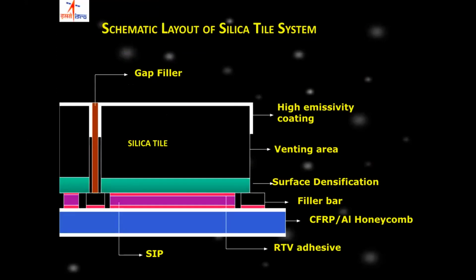And this is the mounting scheme of this tile, because we are fixing the tiles on a metallic structure of the capsule. So you can just appreciate the thermal expansion. Metallic materials expand a lot, but ceramic materials expand very little. So when you are fixing these ceramic tiles on the metallic substrate, which may be aluminum honeycomb of the capsule, then when the heat starts coming on the structure, these tiles will not expand much, but the aluminum structure will expand. And that will create a lot of force and stresses on the interface of these two materials, and these tiles may get chipped away.